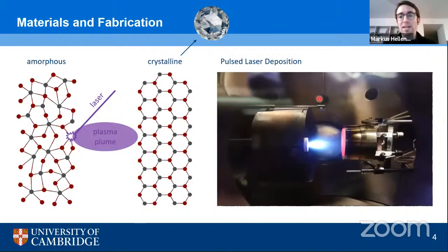So what happens is that the laser shoots short pulses of high energy into this chamber onto what we call a target. So it's this white disk here. This is an amorphous material, and the high energy of the laser evaporates atoms from this material into a plasma plume. And because the chamber is evacuated, so it's under vacuum, the evaporated atoms can travel the length over to this heater here. So you see it glowing bright orange. And by controlling the ambience in this chamber, so the pressure, the energy of the laser, the distance, the temperature, and so on, we can make these evaporated atoms form very nice crystals here on the substrate on the heater.